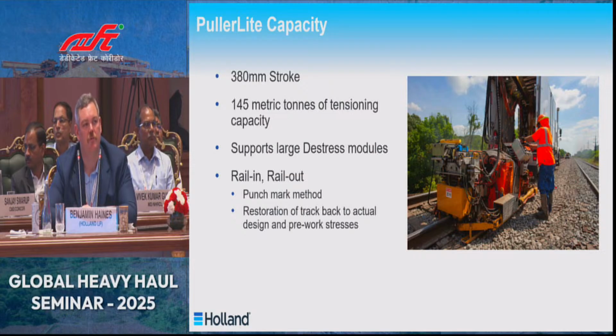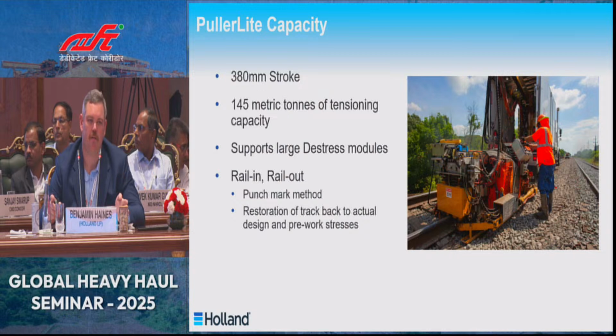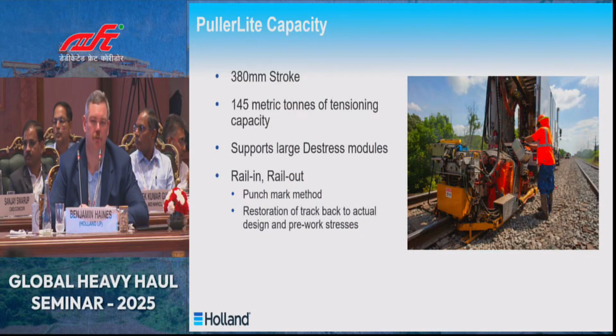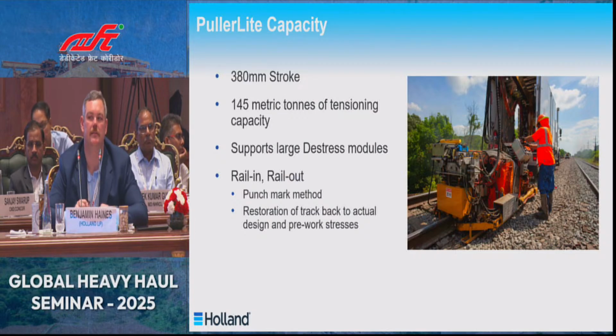We are also able to do the rail-in, rail-out method, which is a punch mark method. If we go to remove a defect, before we cut the track, we can make punch marks, cut the track, remeasure what the movement was, put in a plug, do one field weld, and then come up to the closure weld. Understanding the gap that we need to restore track to its previous stresses, we can do that calculation, overlap the rail, and use the intelligence of the system so that upon the final tensing, we restore track to its original condition.